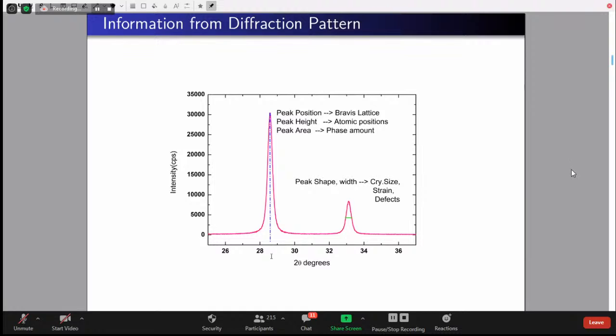So this peak position, not only here but every place, is going to determine the Bravais lattice of the material, whatever Bravais lattice it is. And then the peak heights, otherwise we can say the intensity of the peaks, are going to tell us the positions of the atoms. How this is related is because of the atomic form factors. If you have oxygen, if you have cerium, they have their own different form factors. Together they will give you the height. Now inside the cerium, if I add a little bit of hafnium, then obviously this height is going to either increase or decrease depending on where the atom is sitting.